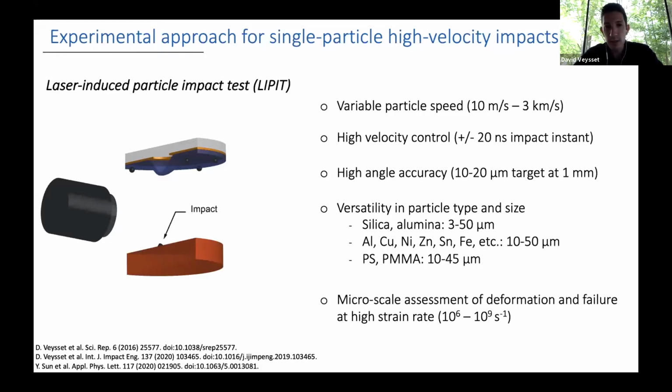So this technique allows us to do microscale study of deformation of targets and particles, and failure at really high strain rates. The strain rate that we're talking about here is 10 to the 6 or 10 to the 9 per second. So this can be related to the previous presentation by Jen, where we can use this apparatus to do high strain rate testing of materials and look at the impact resistance of the materials under impact.